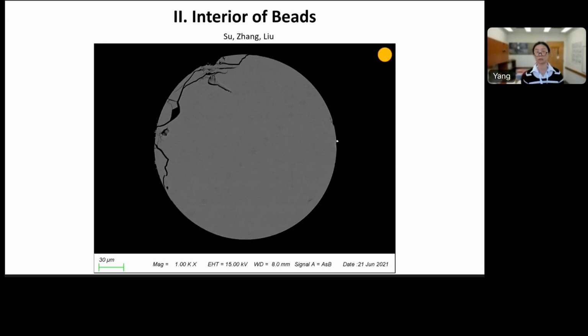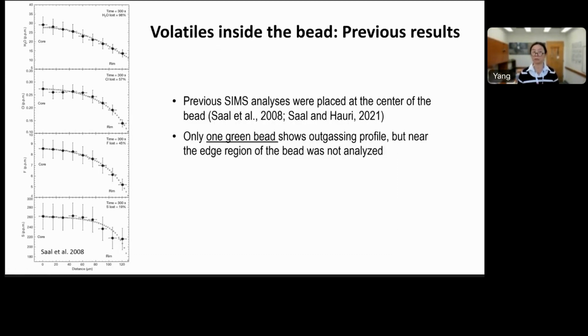Okay, so now let's look at the interior of the bead. As I mentioned before, this work is mainly done by the graduate student at the University of Michigan. This is an image of the interior of an orange bead. It's really glassy and homogeneous with no microlites. Before our study, in the excellent work by Alberto Saal et al., they analyzed volatiles inside the beads with SIMS. Those are usually done by placing the SIMS spot in the center of the bead. Only one green bead in Saal et al.